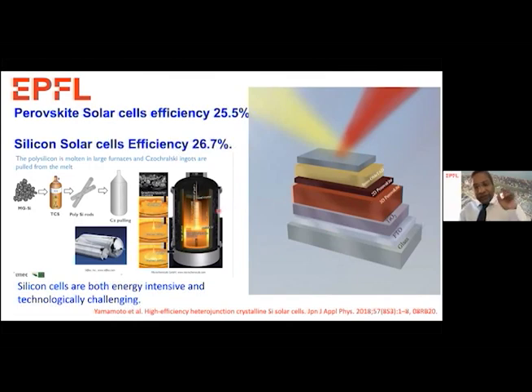The energy input for silicon solar cells is huge. It's 1,400 degrees temperature, which we have to apply to melt metallic silicon and to grow the crystals of silicon material. On the contrary, perovskite solar cells we can fabricate at 120 degrees temperature. The basic energy input is enormous in silicon solar cells compared to perovskite solar cells. Another disadvantage of silicon solar cells, and I'm not saying they are not good, they are excellent, is that they do have an enormous carbon dioxide footprint. For students, you can immediately imagine: producing silicon wafers, converting silicon dioxide into metallic silicon, already produces a huge amount of carbon dioxide. So we have not only the energy input, but also a huge carbon dioxide footprint.